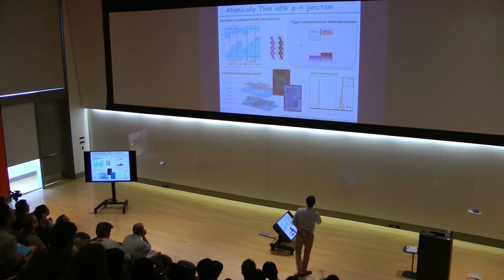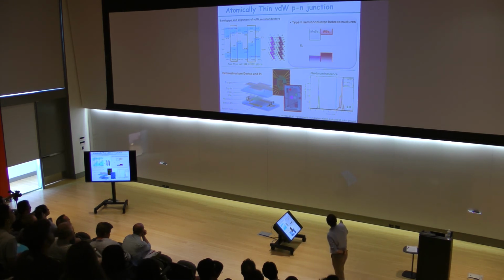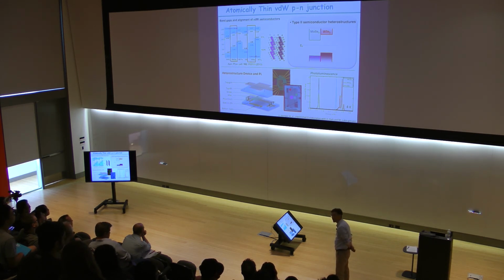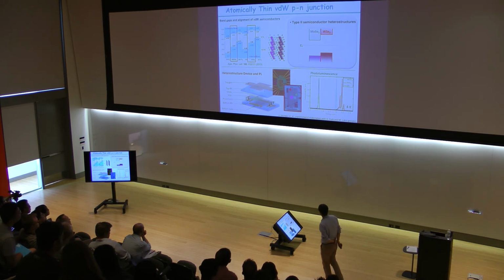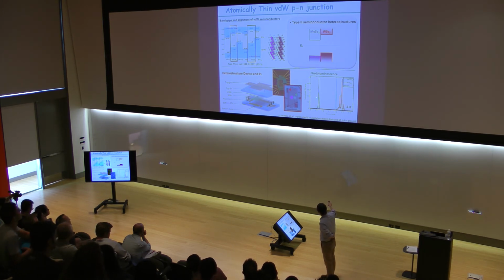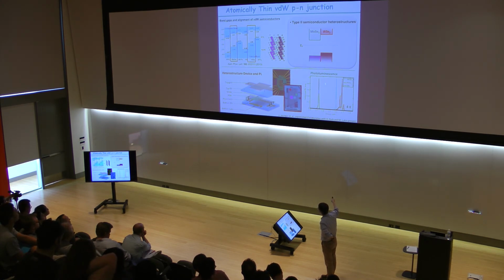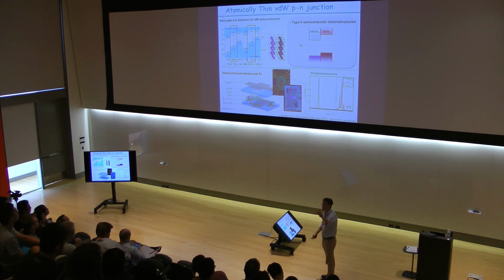Here I'm showing you again the photoluminescence curve. So this one is when we have the tungsten diselenide alone, and this is the molybdenum diselenide alone. At low temperature, the peak width is about a milli-electron volt, almost radiative lifetime limited. But the interesting part is the interlayer exciton. When you have these transitions, we do see that the peak appears in the heterostructure area, indicating that indeed now we have this interlayer exciton formed. And that's an important beginning point, right?